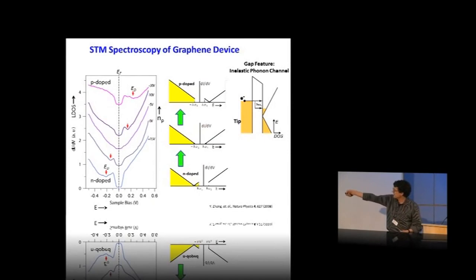Here I show you the data, what we actually saw. This is a plot of dI/dV versus bias voltage between the tip and the surface. This is the Fermi level. And here we have filled states and empty states. And each of these curves is measured at a different gate voltage. And we're becoming more and more p-doped as we go up each additional curve. And so the density of states is sort of shifting to the right as you go up those curves due to the gating. And here we saw two features. One was this gap-like feature that's pinned to the Fermi level, and the other is this asymmetric dip off to one side. Now this gap-like feature is pinned to the Fermi level for different gate voltages.